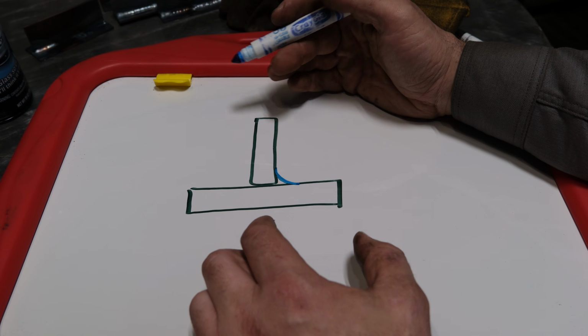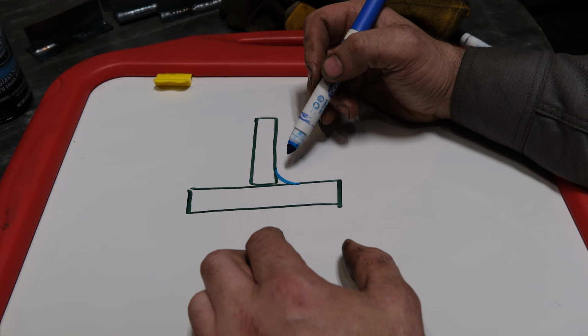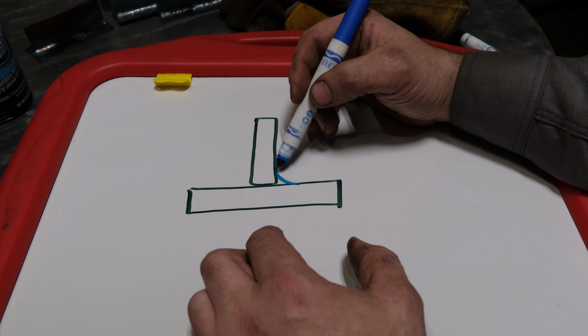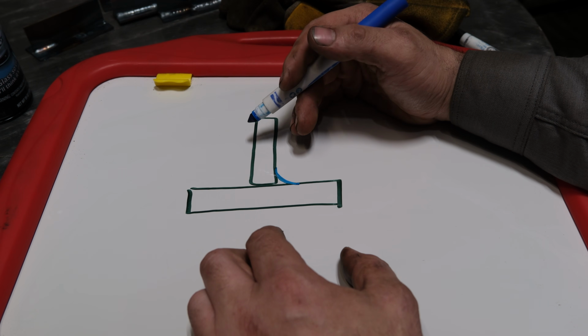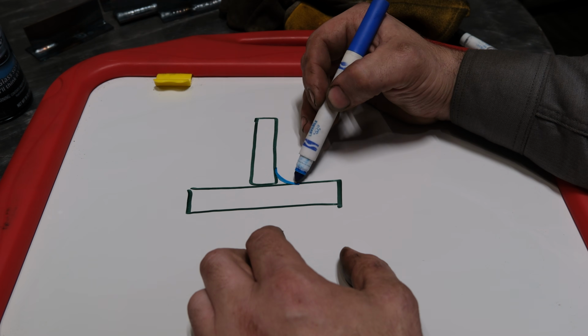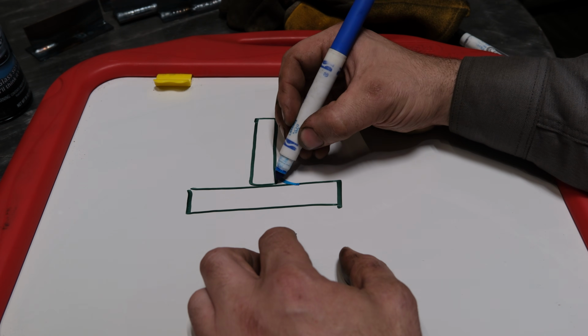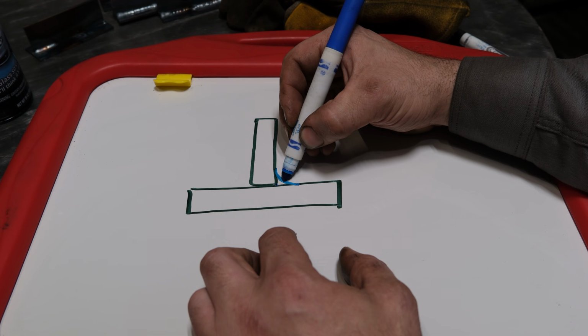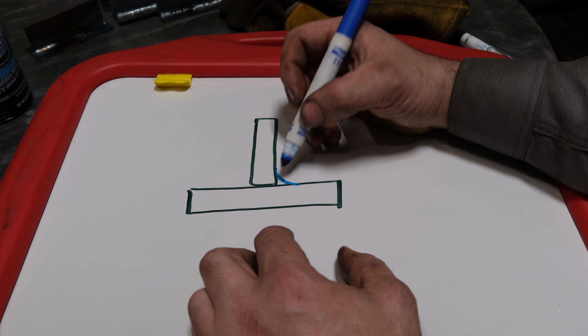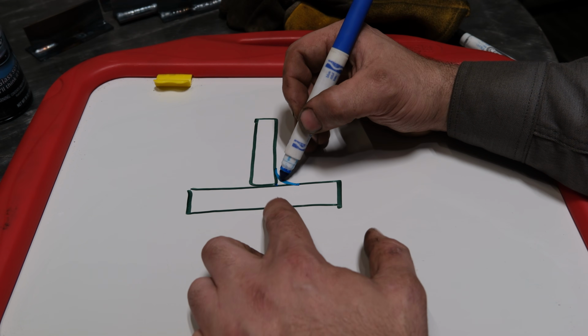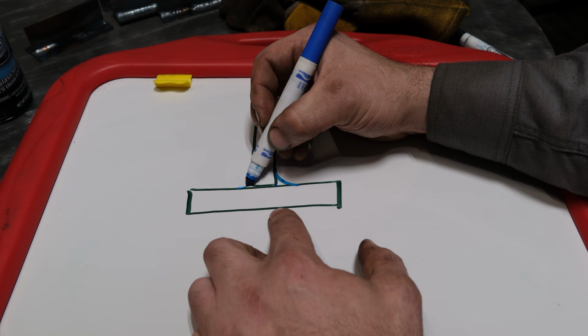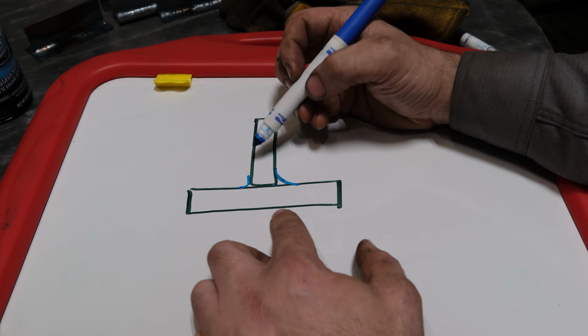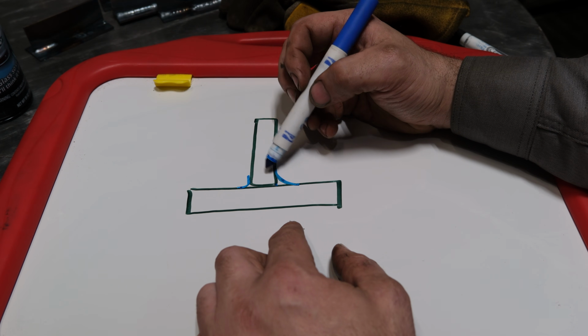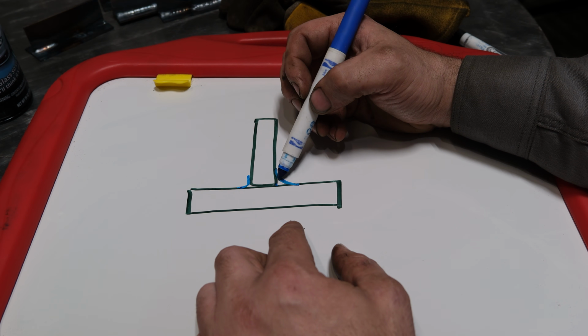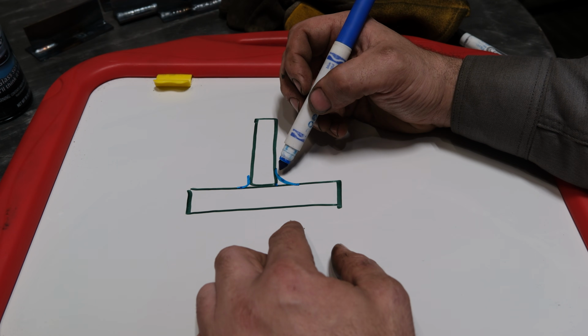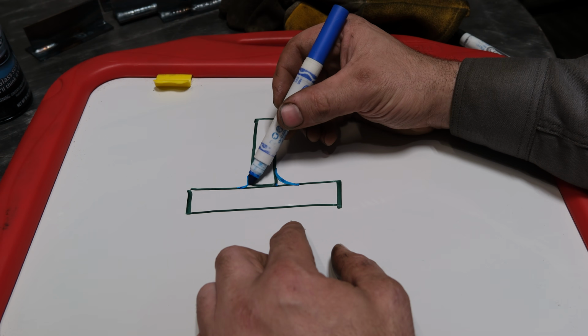So I didn't mention this earlier, and I'm an idiot, so now's a great time to talk about it, and that is having a concave weld. TIG is notorious for making a very concave weld where your throat depth, which is from this point to the center face of that weld, can shorten up significantly like this if you do not push enough filler. So it is absolutely critical that you actually push some filler in there and you don't just touch the filler to the molten pool and think you're good, because your bead will look like this.